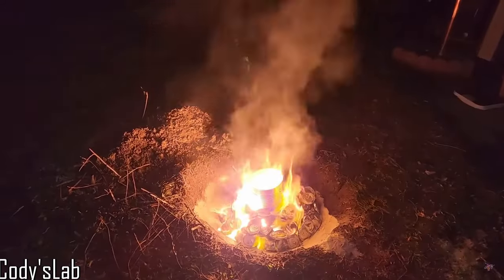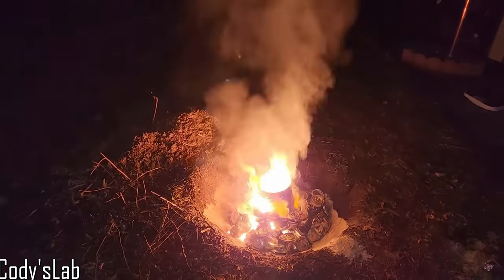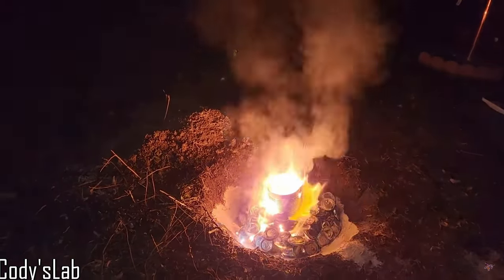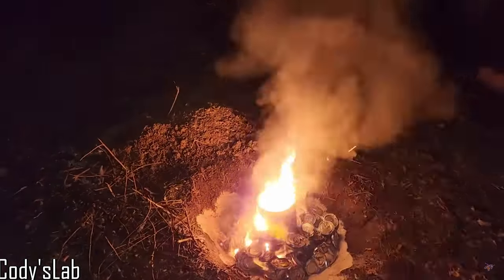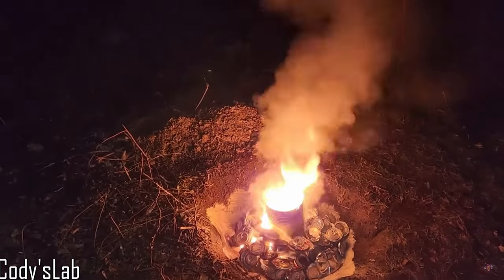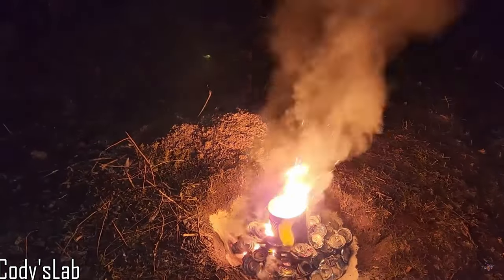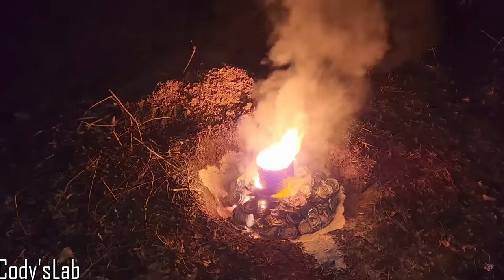Some elements are better at this oxygen collecting game than others, based on their reactivity, and usually iron, the noble window licker that it is, is the slowest and so is left behind, with no one to bond to but itself, shamefully, in the corner. The most common example of this is a thermite reaction, in which pure aluminum metal reacts with iron oxide to form aluminum oxide and pure iron. The aluminum is more reactive than the iron, so it's able to steal the iron's oxygen.